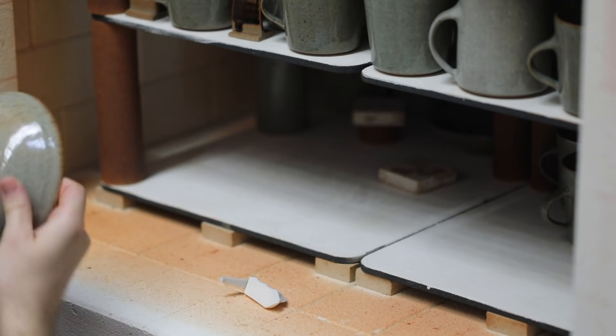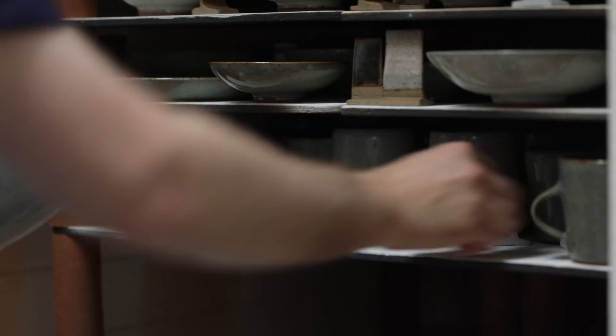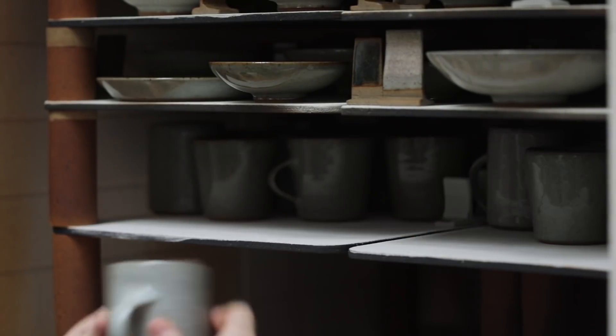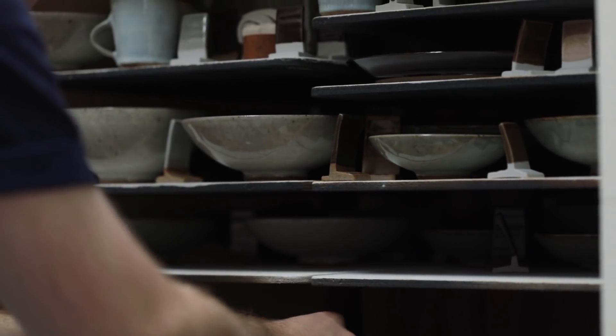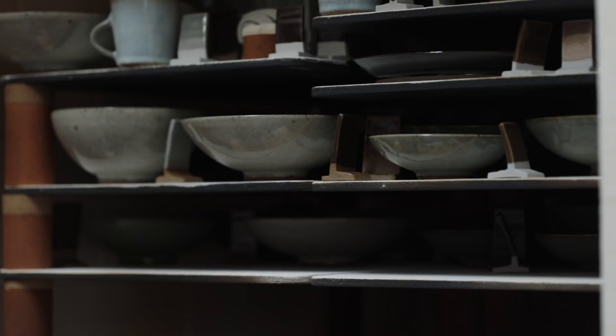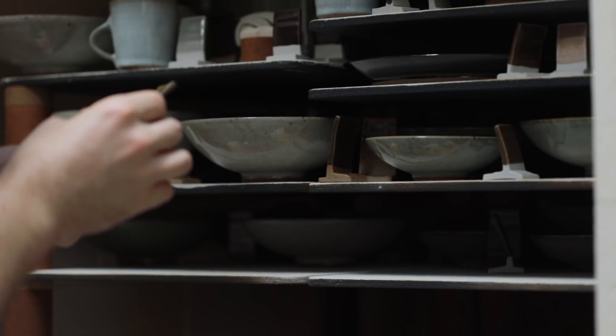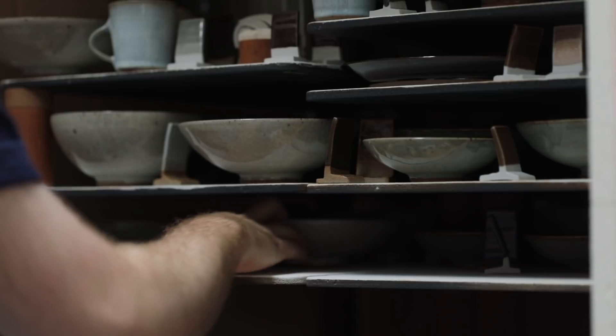Here's one of the plates fired on my new and still very flat silicon carbide kiln shelves, which is something I was waiting for before committing to making a lot more flatware. My previous kiln shelves, which were thicker, were also slightly warped, which meant I'd be firing plates on surfaces that weren't perfectly flat — and as a result, the plates placed onto them would fire and follow the undulations of the shelves themselves.